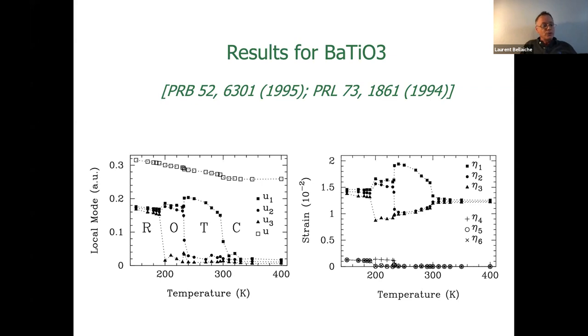So it was the first application of this effective Hamiltonian in barium titanate. It was done, and it was very nice that you can reproduce the experimental phase transition sequence. Be careful, you don't reproduce a phase transition sequence well most of the time. It depends on the system you are looking at.